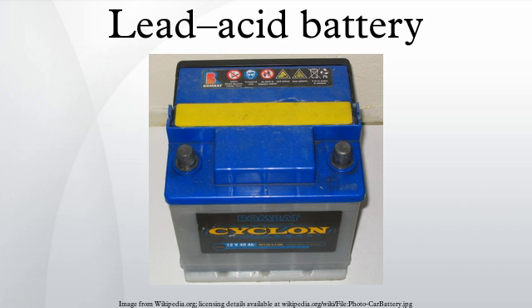Sulfation and desulfation. Lead-acid batteries lose the ability to accept a charge when discharged for too long due to sulfation, the crystallization of lead sulfate. They generate electricity through a double sulfate chemical reaction. Lead and lead dioxide, the active materials on the battery's plates, react with sulfuric acid in the electrolyte to form lead sulfate. The lead sulfate first forms in a finely divided, amorphous state, and easily reverts to lead, lead dioxide and sulfuric acid when the battery recharges.